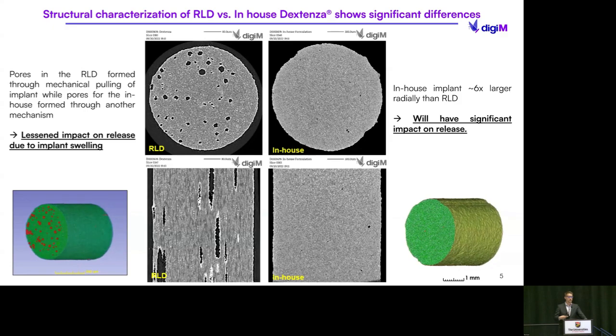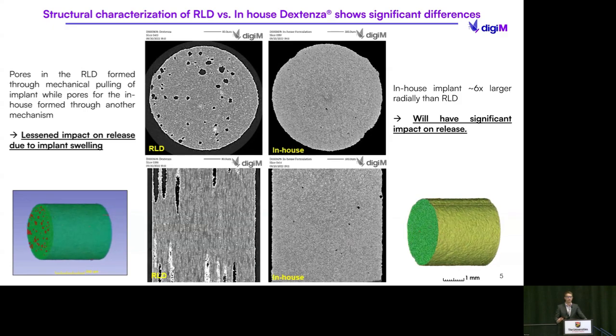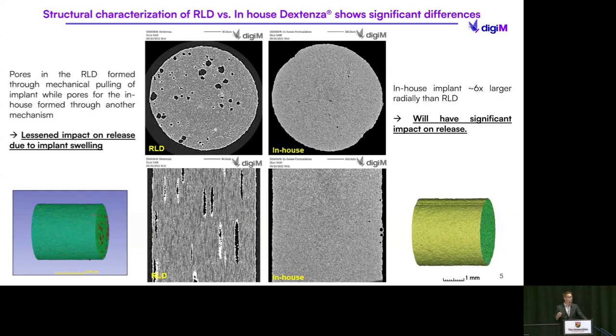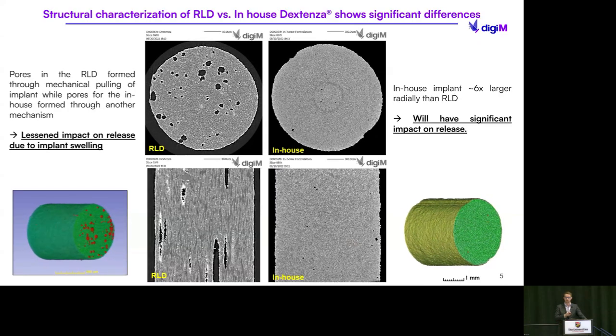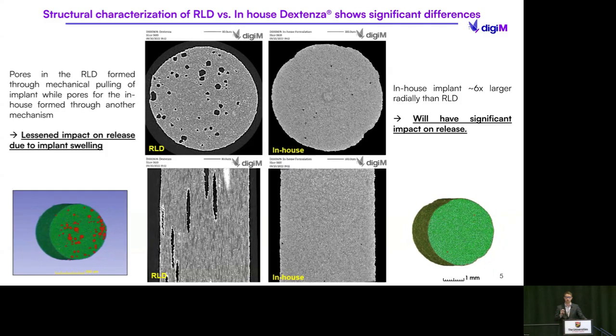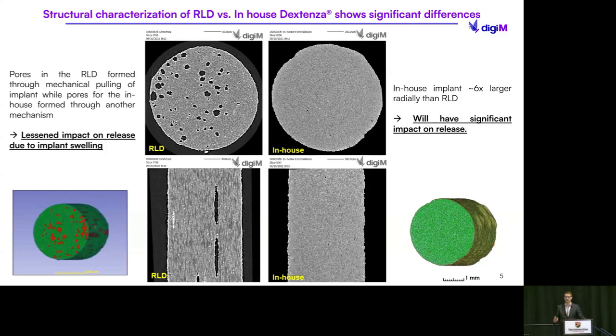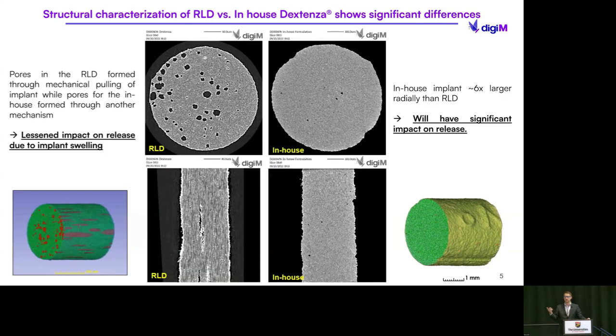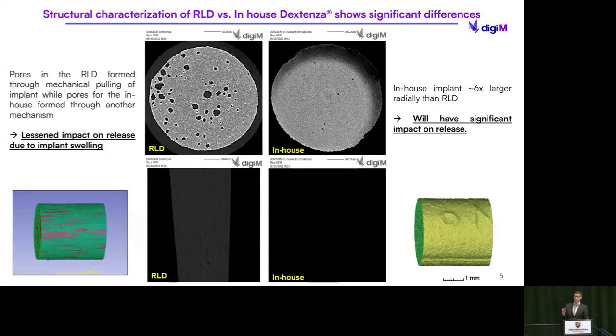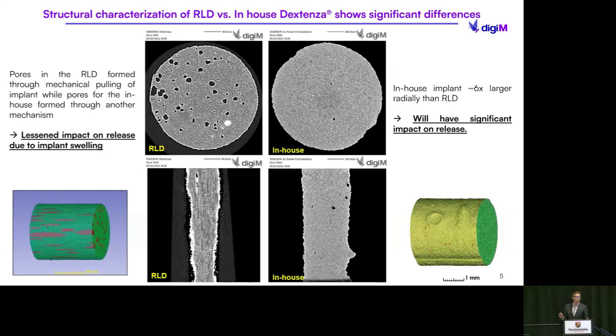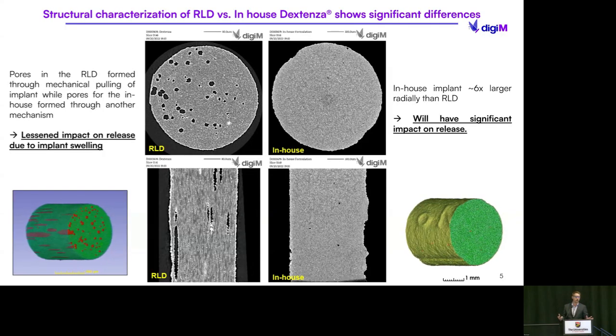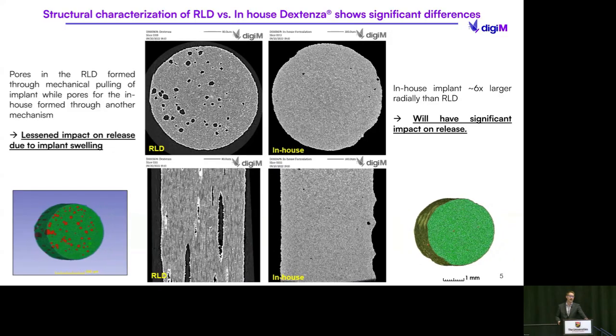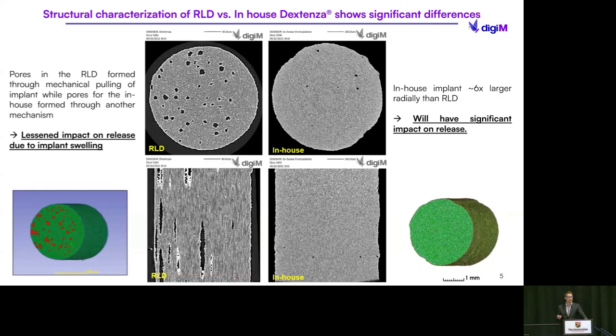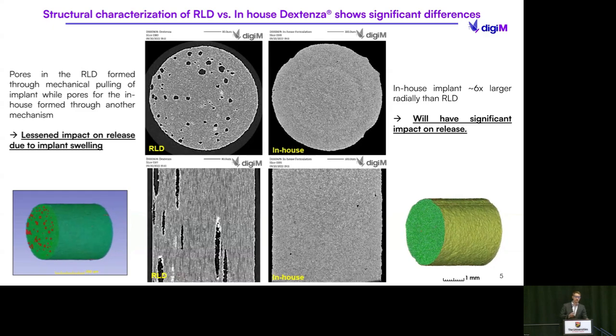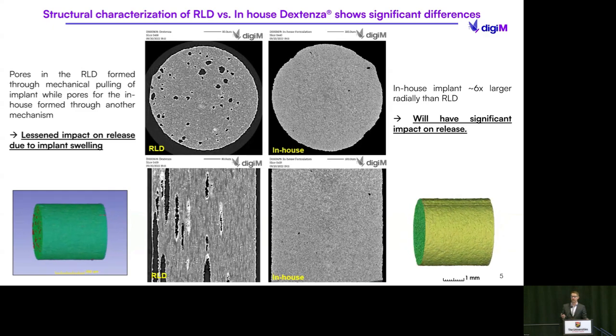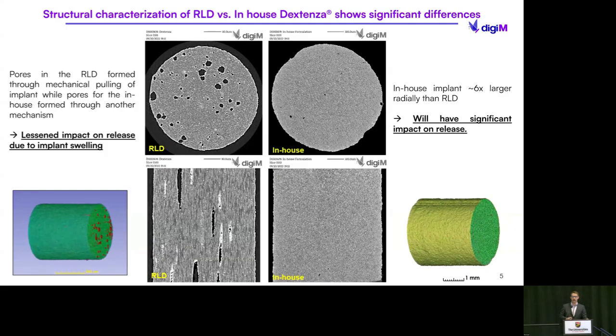If these behave through monolithic diffusion or any kind of diffusion limited process, then these pores are actually going to matter quite significantly when it comes to the overall release. They provide a highway for any dexamethasone to rapidly escape through. Whereas in the in-house one, you have significantly fewer pores, so you don't have any of these highways to diffuse along, and you also have a longer diffusion path to go across. So will this have a significant impact on release? Porosity is arguably, in every case, a critical quality attribute, but is it the most critical attribute?